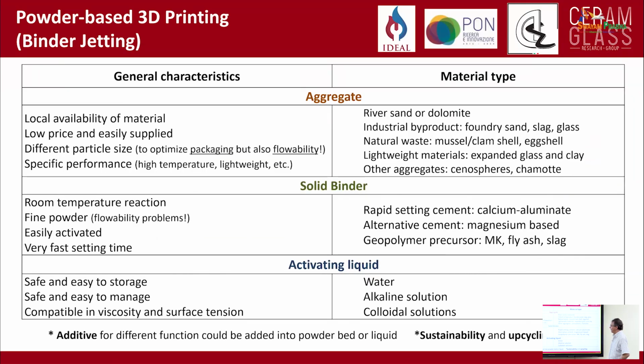We worked on different projects using this approach, and we have this solid binder, which is metakaolin, and which is highly reactive. I already told you the size of metakaolin powder, 6 microns by a few hundred nanometers. So very fine powder, like flour. And you know that this is non-flowable. So we cannot generate a powder bed of pure metakaolin.